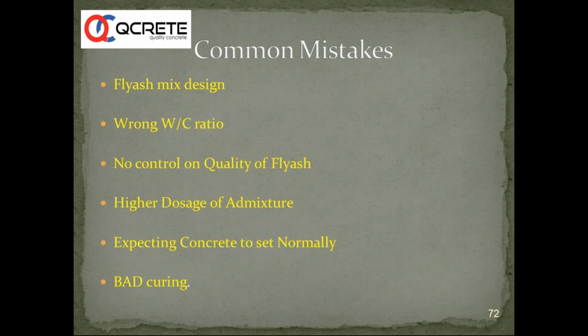So the cracks were retamped, revibrated, and then over this, the customer asked the contractor to apply a curing compound. After the curing compound was applied, a plastic sheet was also put, and then on the plastic sheet, he was putting a lot of water to keep the entire concrete slab cool in a hot climate like Chennai. So we need to have continuous curing and extended curing periods because we are taking advantage.